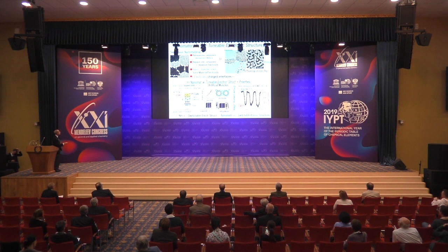And now we fill an aqueous electrolyte into these voids, and then we can apply a voltage between the electrolyte and the metal, the gold, for example. If you do that, then of course we get electric charges at these interfaces, and as 50% of the atoms are sitting in these interfaces due to the nanometer-scale structure, 50% of the atoms can be changed in their electronic charge. So we can tune the charge of the atoms by applying the voltage. And that, of course, changes the properties.